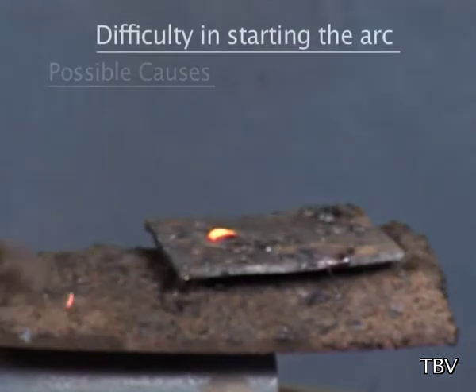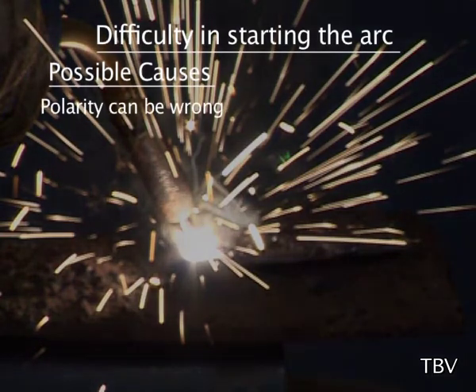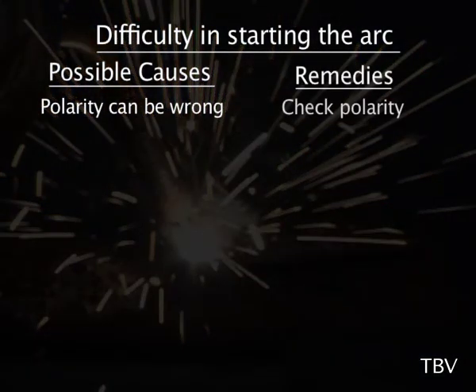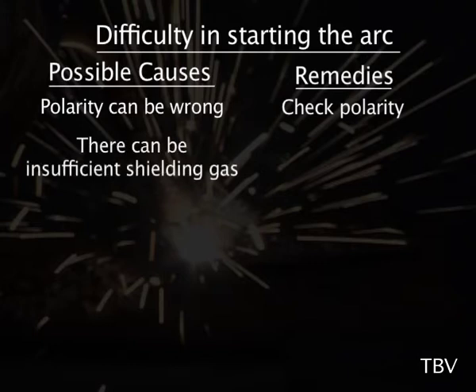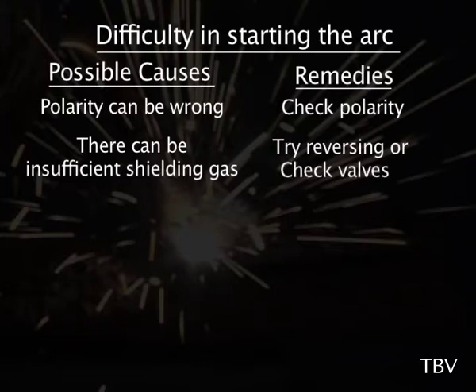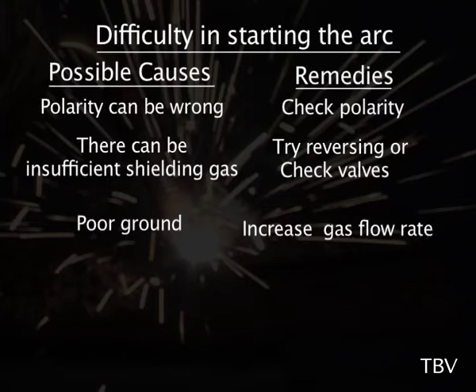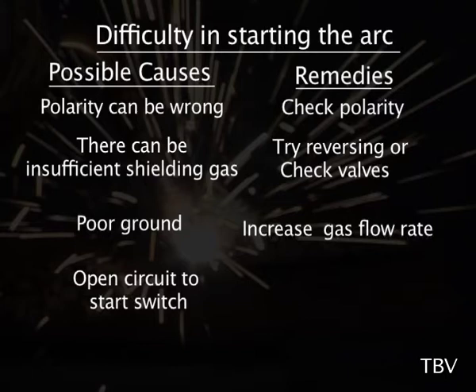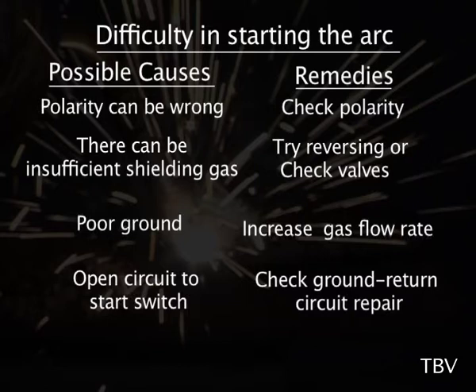Weld defects, causes and remedies in CO2 welding or GMAW. Defect: difficulty in starting the arc. Possible cause: polarity can be wrong. Remedy: check polarity. There can be insufficient shielding gas. Remedy: try reversing check valves. Poor ground. Remedy: increase the gas flow rate. Open circuit to start switch. Remedy: check ground return circuit repair.